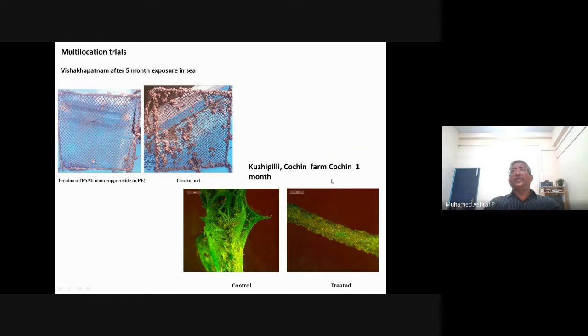And then after the success of this one, we tried multi-location studies. We kept the treated material in the Visakhapatnam Sea, Vizag Sea, for 5 months, and these are the results. You can see the untreated control has a lot of fouling organisms, and this treated one has a very limited number, and it is highly efficient. And apart from that, at another place near a freshwater system, we have seen similar results. We kept it only 1 month, and you could find a lot of algal accumulation over this, and here you will find very little.